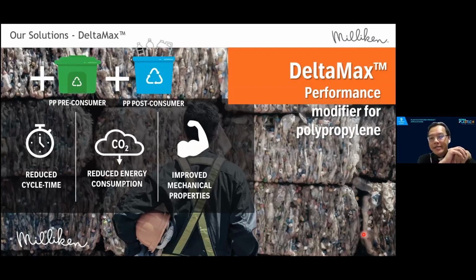And one of the areas that we see could be interesting is upgrading the recycled impact copolymer polypropylene. Delta Max is not only for recycled, but recycled PP is still PP. If there is impact copolymer recycled in the stream, you can also use Delta Max to improve the recycle stream, because whether it's pre-consumer or post-consumer, recycle stream generally has more variability in MFR and more variability in impact strength. And if we can upgrade that, we can use it to make the variability in the incoming stream easier to process.